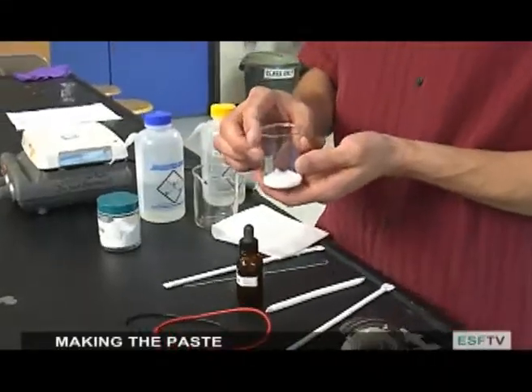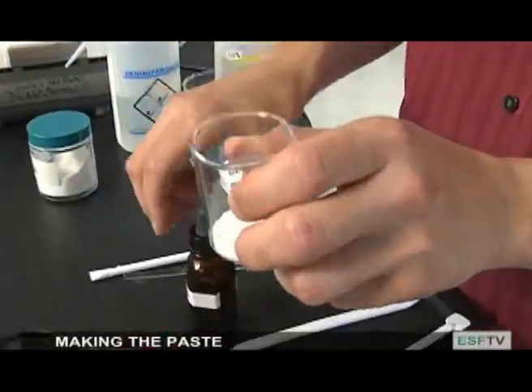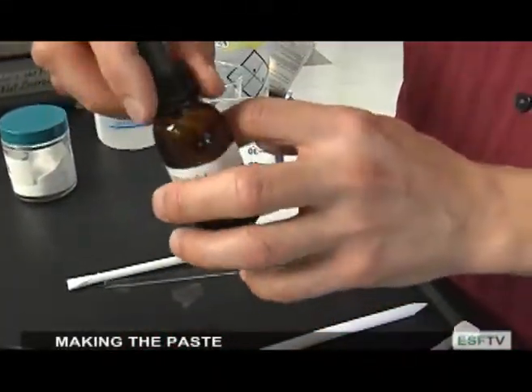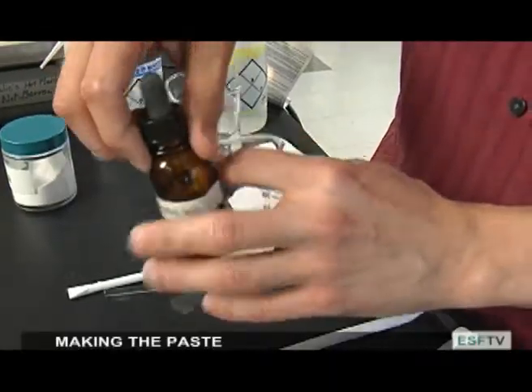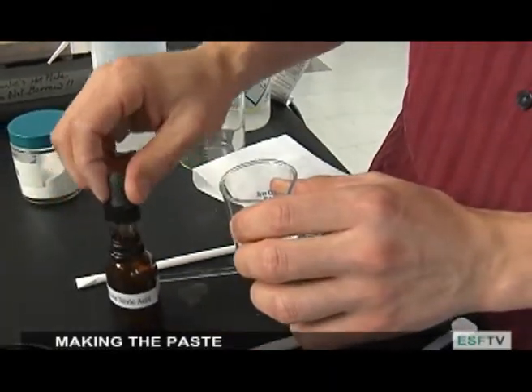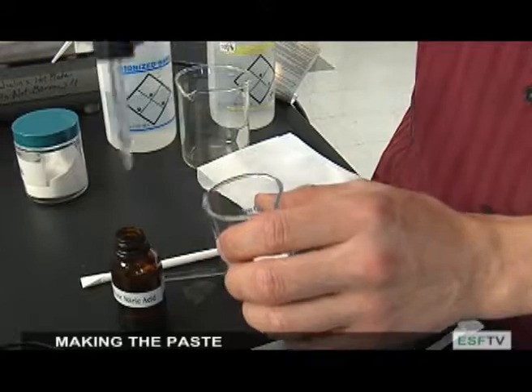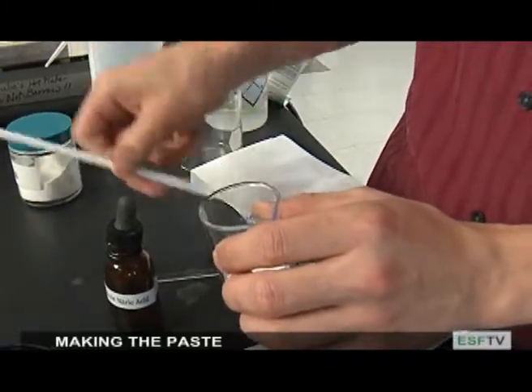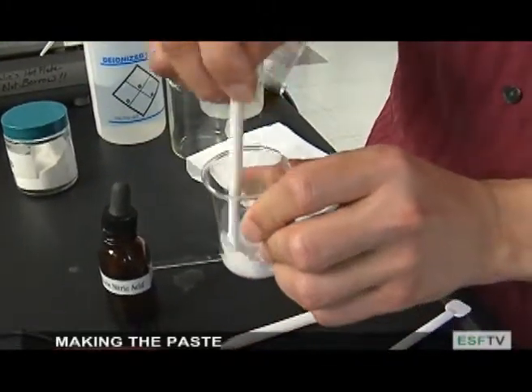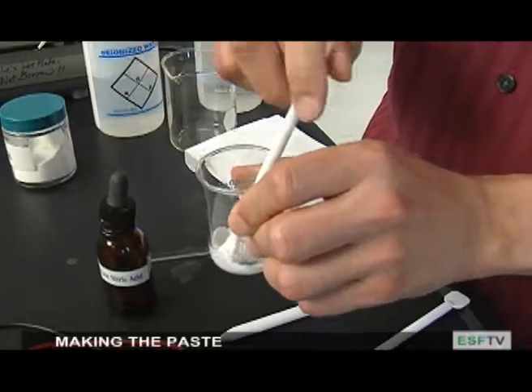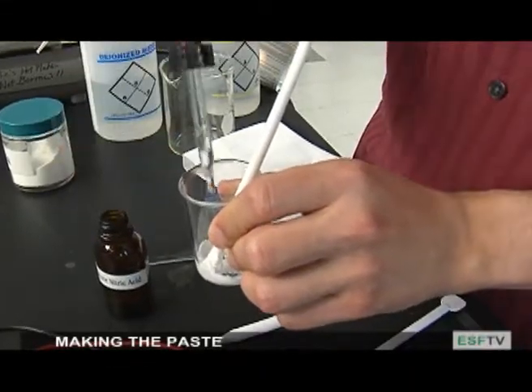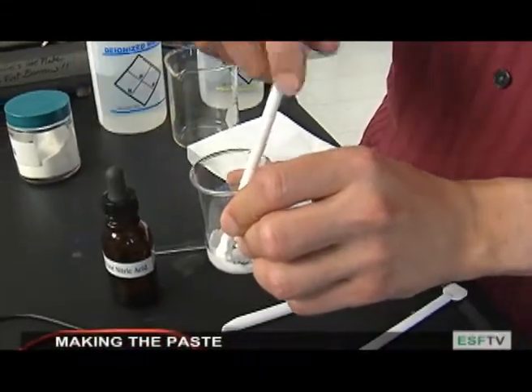I've placed some titania paste inside this beaker, and we're going to make a slurry using some nitric acid, dilute nitric acid. The slurry should be a little thicker than water, but thinner than paste. So I'm going to add some of the acid and slowly stir until we get the right consistency.